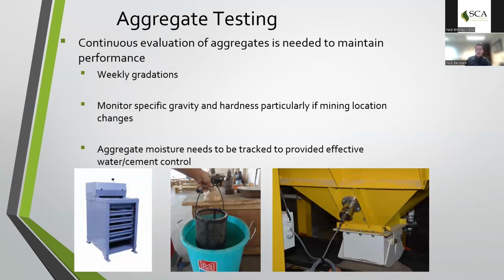Along with that, control charts are a great way to help control different outputs on your aggregates and can really help individual technicians make those adjustments collectively and with good guidance. Along with that, monitoring of moisture is the other main production factor that we try to manage. Most plants are set up with live moisture probes, mostly on fine aggregate, but we are starting to deploy coarse aggregate moisture probes, and overall our experience with that has been very helpful. And again, helping keep a more consistent blend to the material in terms of aggregates and the moistures that they carry, leading to more consistent concrete production.